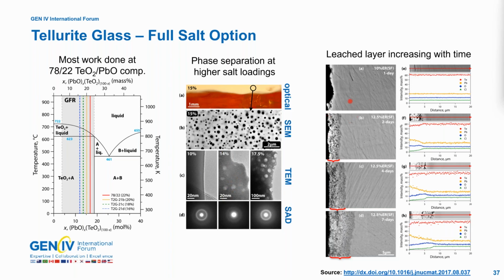These are C1308 tests that were run on coupons of tellurite glass. And you can see that this is the penetration layer where the chlorine is actually being depleted from these different glass coupons. So this is some graphics that can be used to track corrosion, and then we use EDS dot maps to track compositional changes within the coupon at that interface boundary layer.